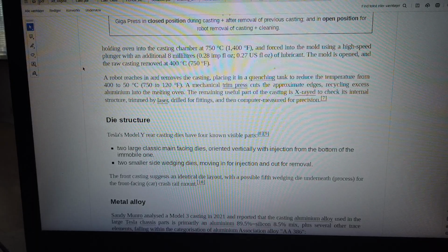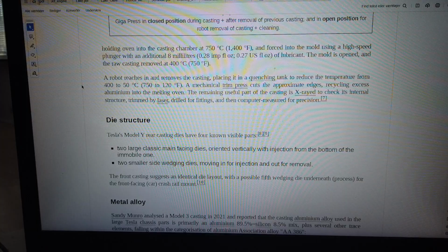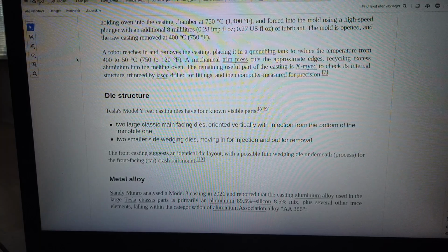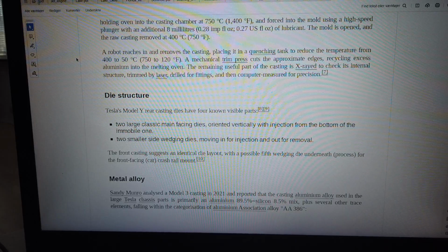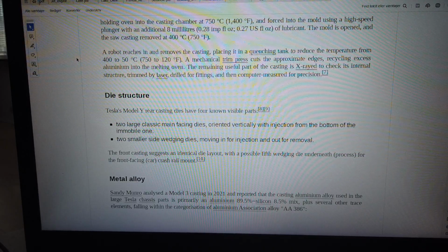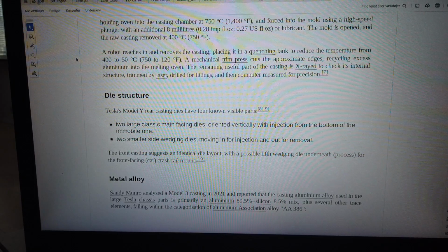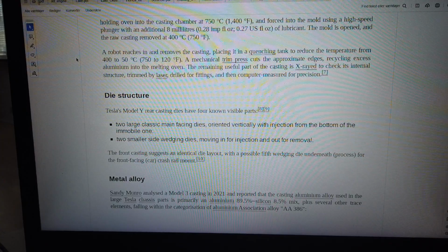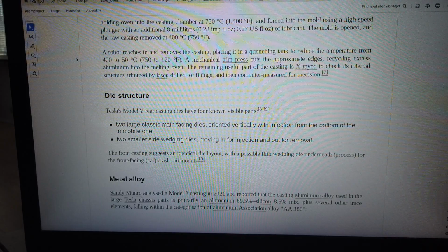The mold is opened, and the casting is removed at 400 degrees Celsius, 750 degrees Fahrenheit. A robot reaches in and removes the casting, placing it in a quenching tank to reduce the temperature from 400 to 50 degrees Celsius, 750 to 120 degrees Fahrenheit. A mechanical trim press cuts the approximate edges, recycling excess aluminium into the melting oven. The remaining useful part of the casting is X-rayed to check its internal structure, trimmed by laser, drilled for fittings, and then computer measured for precision.